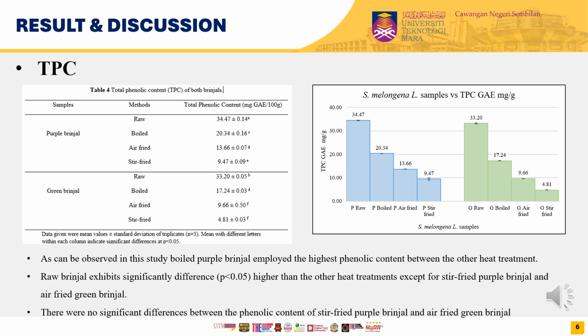From the tabulated data and the graph, we can observe that the boiling heat treatment method had the highest phenolic content, and the stir fry is the lowest phenolic content among the heat treatments. As we can observe, purple brinjal has the highest phenolic content, higher than green brinjal.